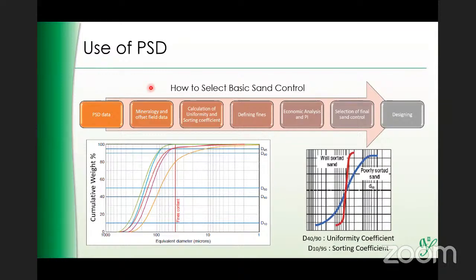So basically what we do is we get the PSD data and see whether the sand is well sorted. If it is well sorted, the difference in size between the largest particle and the smallest particle will not be great, as you see in this vertical graph. And if it is a smooth graph as here, then it is very poorly sorted. You will have a very high sorting coefficient and a very high uniformity coefficient.